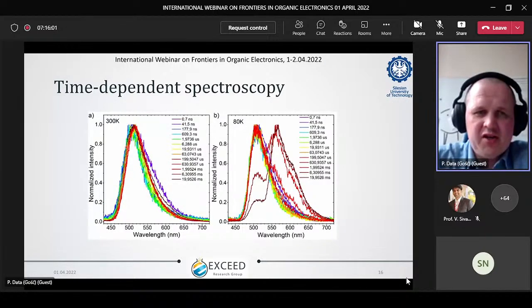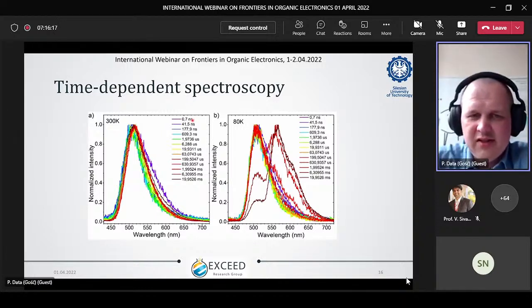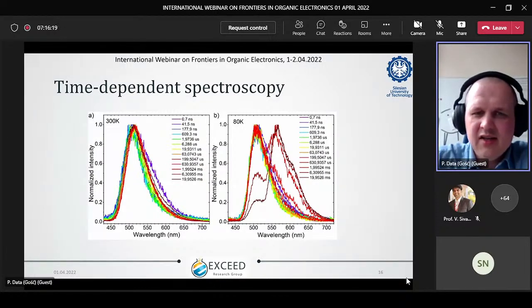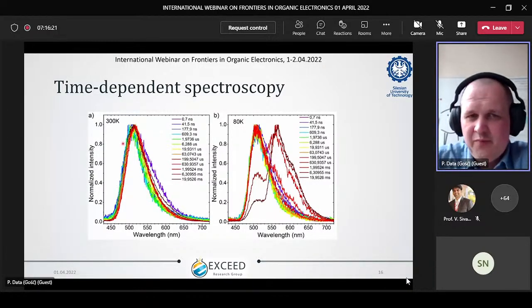Moreover, if you will check how the same molecule behaves at 300 Kelvin, so room temperature, at different delay times, you see that from less than nanoseconds up to 20 milliseconds, the spectra is almost the same. So again, we have very nice delayed fluorescence. But if we cool down to 80 Kelvins, we see that in the beginning we have phosphorescence.